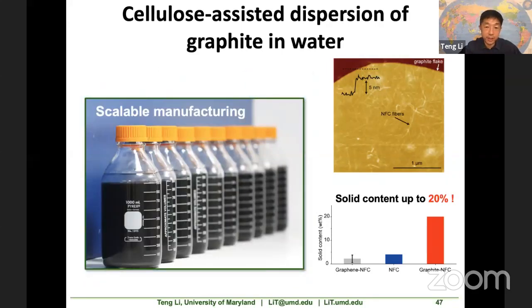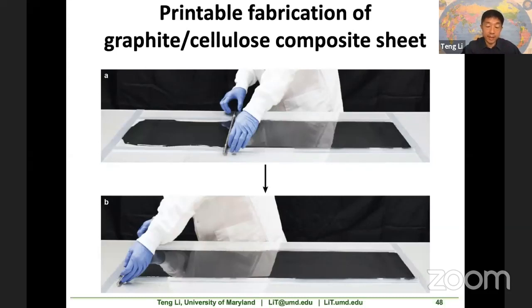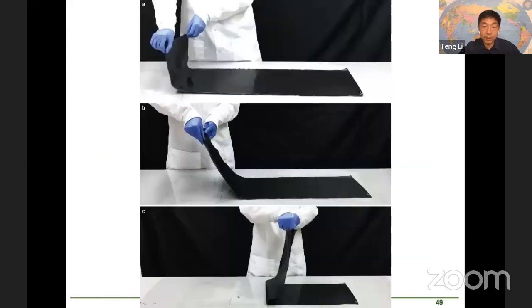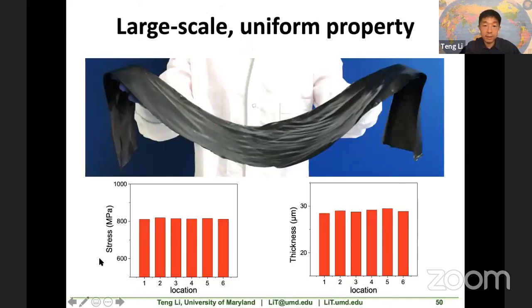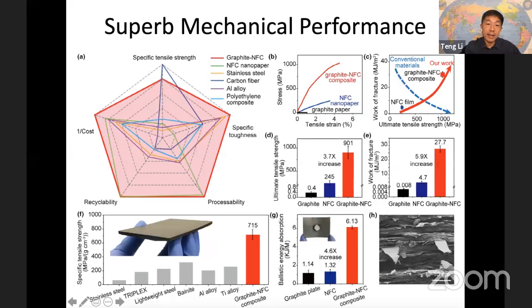And you can make this at large scale. Because of the thick nature, the viscosity is high enough that it allows us to print this into a large film. When you dry it and peel it off, you can make this like a scarf, 1.2 meters long, 30 centimeters or 1 foot in width, a fabric-like thin film. The property is actually uniform. We picked 6 random locations and tested their properties. They are rather uniform. And in terms of mechanical performance, cost, recyclability, processability, and specific toughness, it is shown as the red color here, and it is actually better than many other materials.